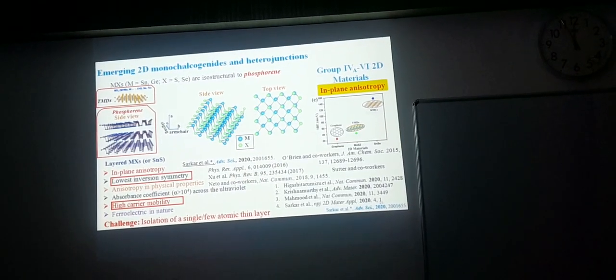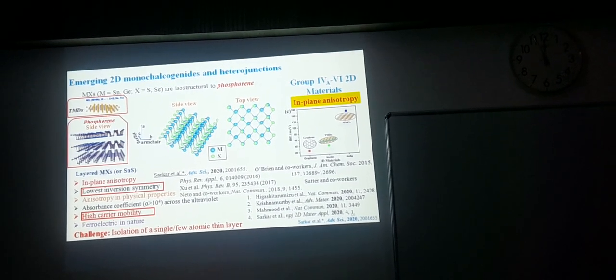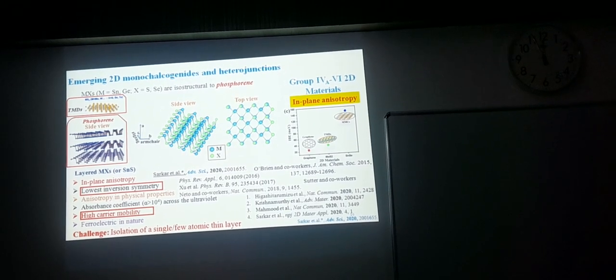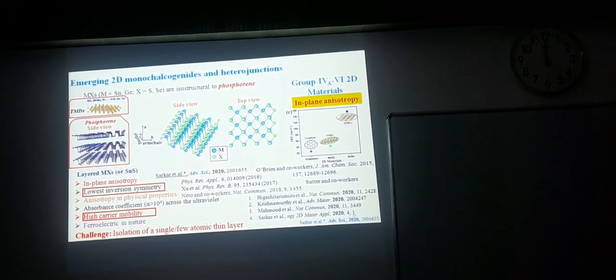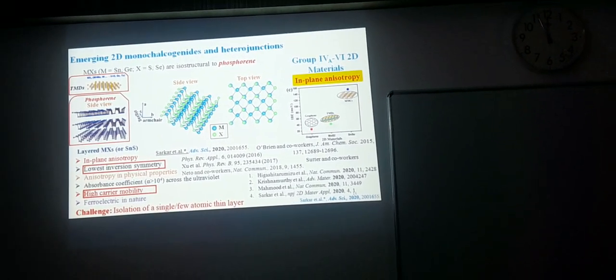And also it has a very specific crystal symmetry that I will come to in later slides. So it has a very low crystal symmetry, and crystal symmetry is very important in fundamental physics in terms of optical and electronic properties. So that is very critical for these materials. Also, this material is quite stable, as mentioned by the professors in the inauguration, the stability or environmental acceptance of materials is very important for real application. So this material is quite stable. Here I basically talk about the low crystal symmetry, the high carrier mobility, and also the absorption coefficient or absorbance of these materials in the next slide.